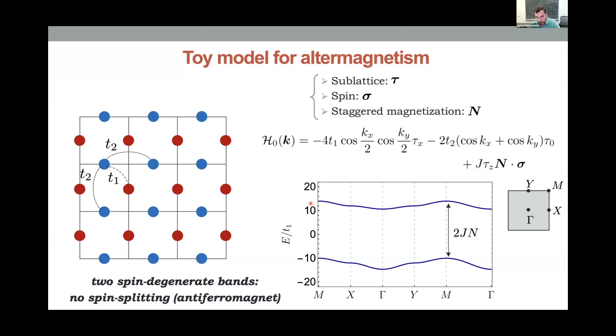You probably cannot really see, but the blue and red bands are on top of each other. There's a splitting that is set by this exchange coupling, but that's it. You didn't split the bands. And the issue is because I actually haven't implemented the symmetries of this lattice. Just by writing it down in a bigger unit cell does not impose that. I need to have something else. The lattice needs to enforce the symmetries on these atoms.